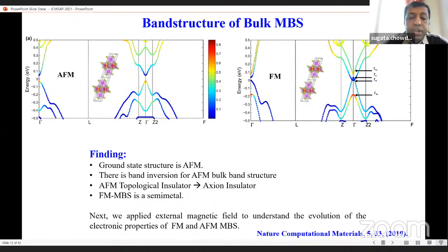So what is going on? What are the things we found? Its ground state is antiferromagnetic, and it shows an axion insulator. But if you look at the band structure, ferromagnetic and antiferromagnetic, the antiferromagnetic is an insulator and there is a band inversion. On the other hand, the ferromagnetic system is semi-metallic, and if you notice, the bands cross around the gamma point at two points, and these two points are called Weyl nodes, and hence it is called a Weyl semimetal.